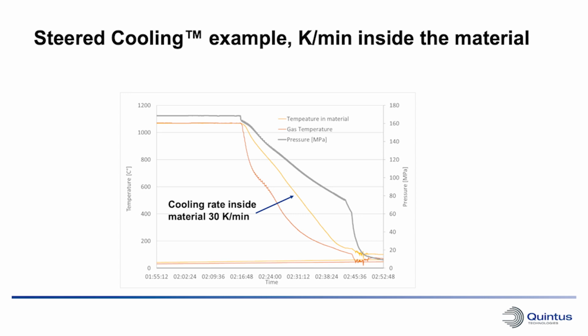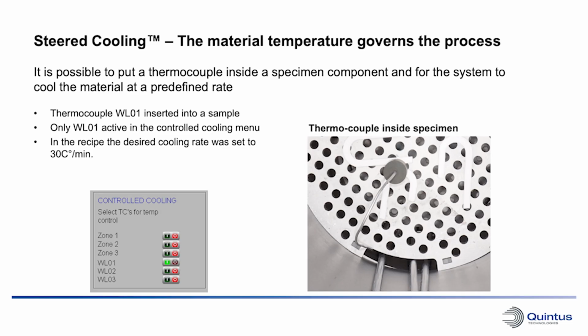So you can set that cooling temperature actually between 0 to 300 degrees, and what you want in the gas. Or if you take one of the thermocouples and put it inside a part, you can steer with that. You can actually control the cooling rate of that part instead. Okay, so you can actually measure the temperature inside a part. Yeah, if you put a thermocouple inside a part, you can do that.